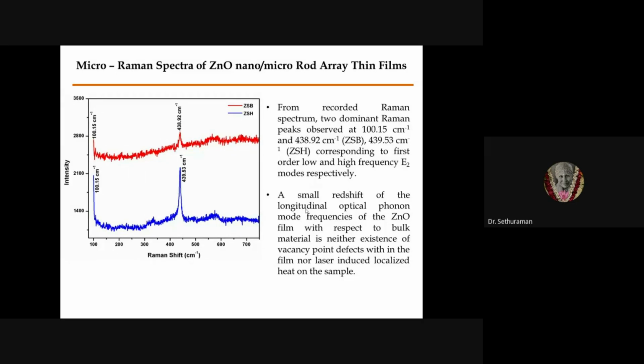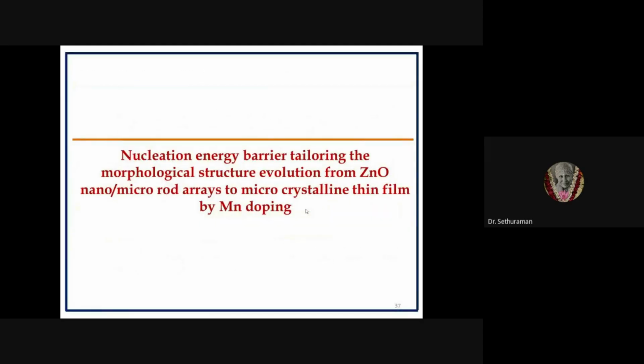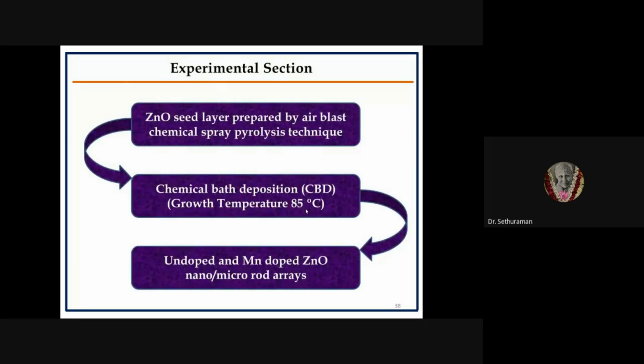It may be due to the longitudinal optical phonon mode frequency of the zinc oxide with respect to the bulk material. Some conclusions: here, regarding the nucleation energy barrier, we are tailoring the morphological structure evolution of zinc oxide nano micro rod arrays by using Mn doping. Here we are using Mn as a dopant. What happens to the solution as well as the supersaturation? How the seed layer is important, playing a very important role, and how the metal dopant as well as the seed layer play a very important role in the growth of the zinc oxide nanorod assembly on the glass substrate.